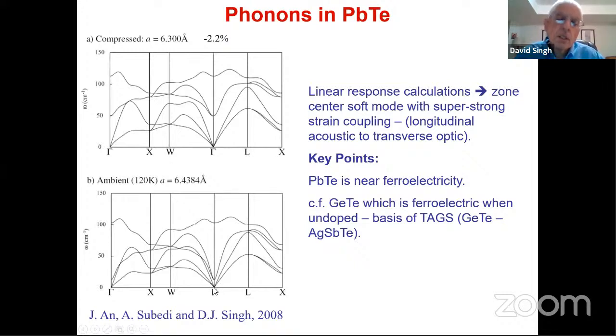And what you see, it's a solid. So there's a compression wave. So that's this longitudinal acoustic mode, it's called. This is the compression wave. It's the wave that carries speech in air. It's compression waves. All right. But in a solid, you can also have shear waves that propagate, and these are the transverse acoustic waves. And they also have a velocity. They rise with momentum, but not as quickly, so the velocity is lower. So it turns out that high velocity is good for carrying heat, and so this longitudinal acoustic wave is the one that carries most of the heat.